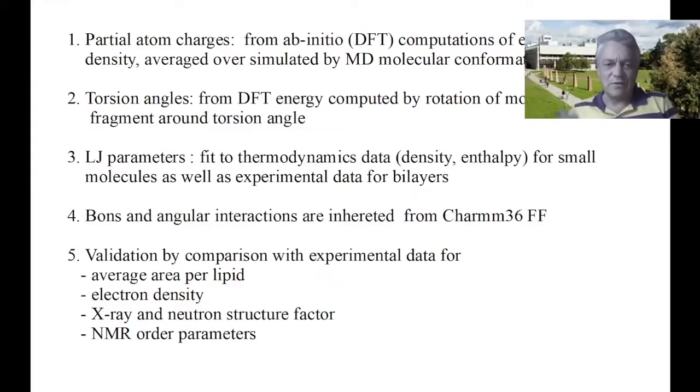One needs to go to very advanced quantum theory, but then it takes a very long time for computation. So Lennard-Jones parameters essentially were fitted to reproduce experimental thermodynamic data for small molecules representing corresponding parts of lipids, fitted to density and enthalpy data, and finally to some experimental data for bilayers.